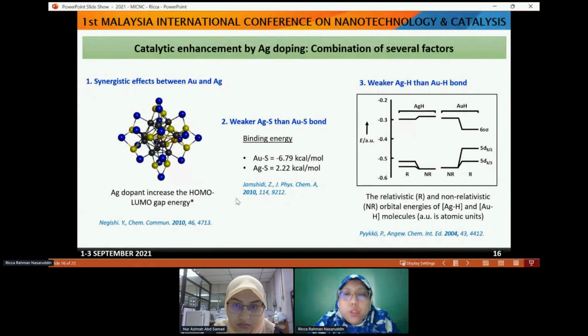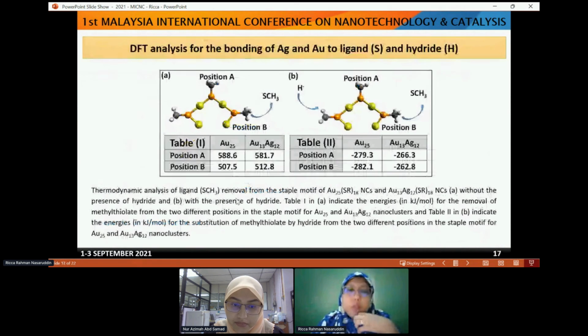And we also realize there is a weaker silver hydride bond than gold hydride bond. So what happens if it is weaker? It means it will be easier to do the catalytic activity. Hydride, based on our previous study, I will show you later, but this is the DFT analysis to confirm the weak interaction between gold and sulfur, and silver and sulfur.